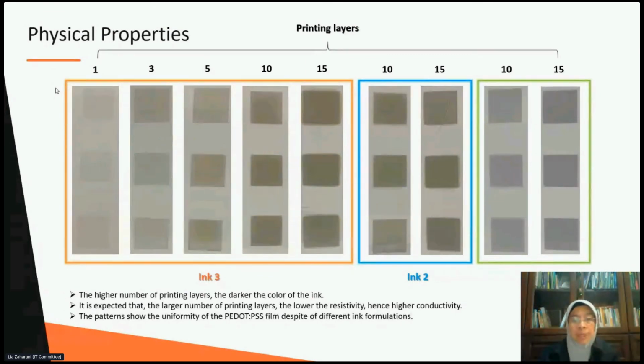It is expected that the larger the number of printing layers, the lower the resistivity. When the resistivity is lower, of course, the conductivity is higher. So the pattern shows the uniformity of the PEDOT:PSS film despite the different formulations. We would like to see the electrical properties of our inkjet printing on the material. As mentioned earlier, we have formulations for ink 1, ink 2, and ink 3, and a control here for the fabric only.